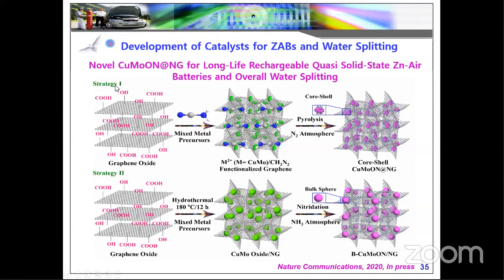When we are going for strategy 1, that method is very simple. We mix the initial precursors of graphene oxide and metal precursors, and finally we get some intermediates, and finally we pyrolyze them in a nitrogen or argon atmosphere. No hazardous sources are used for the development of the catalyst.